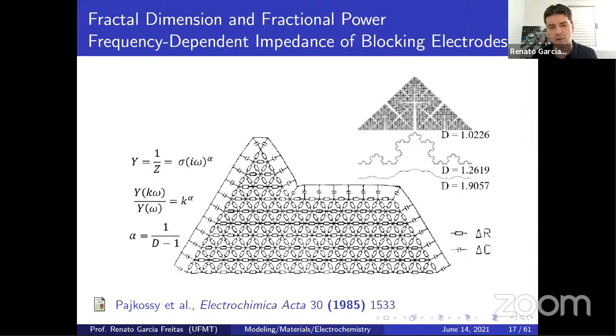I worked personally with a colleague of Pajkossy, and he says the experiment of Pajkossy took a week just to clean the golden surface of the single crystal, to obtain a very clean surface and avoid all the boundary conditions, to obtain a very flat, perfectly smooth surface. But it's not possible. As you see, we have the attached electrolyte species and we have the fractal dimension.